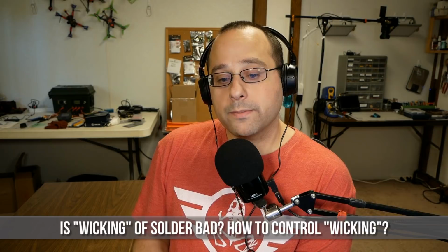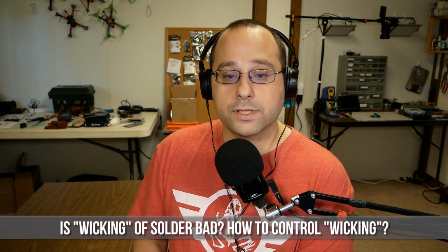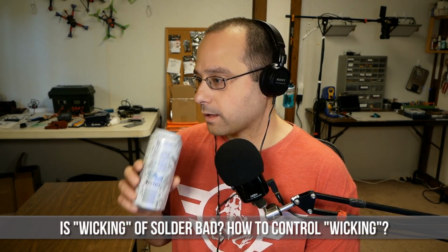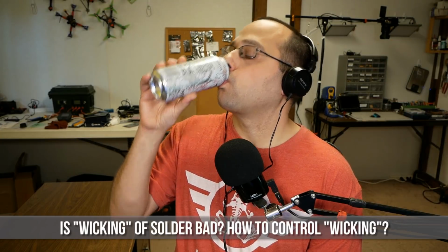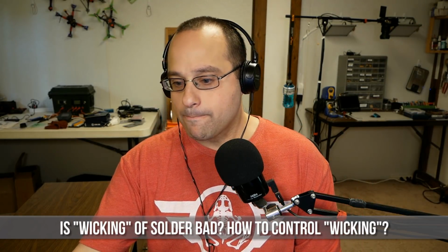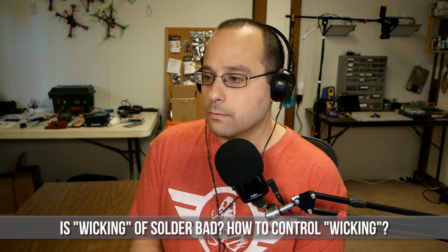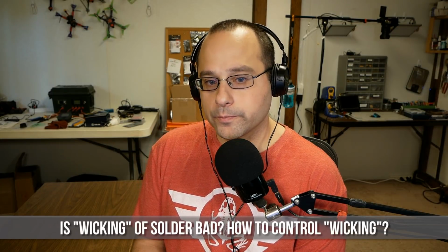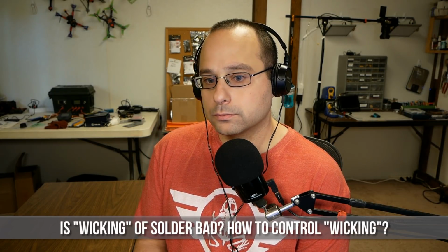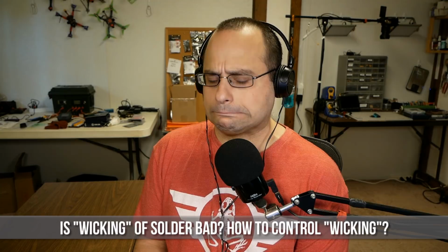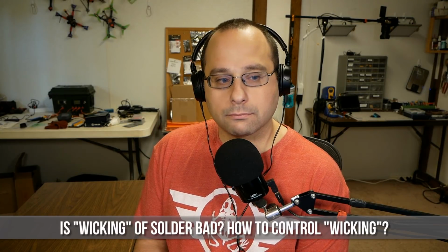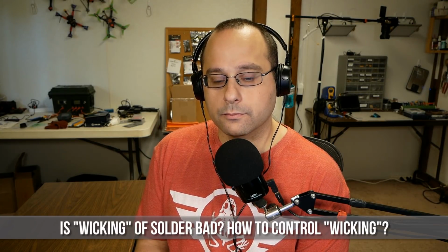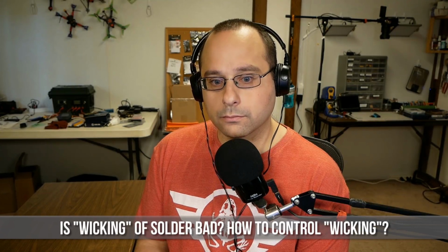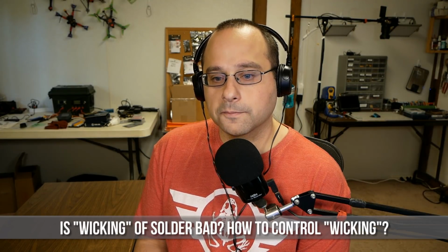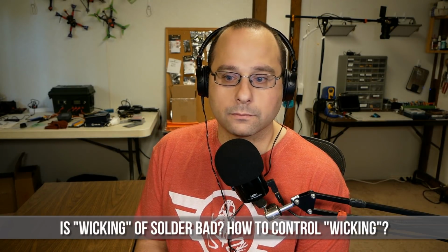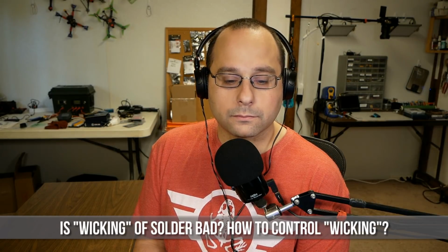What can you do to minimize this wicking if you do desire to minimize it? So you could use a 60-40 solder, which will minimize that wicking because it doesn't flow as much as a 63-37. You could also use some of the lead-free solders, which also don't wick as much as the 63-37, like a tin silver, like a 96.5 tin, 3.5 silver, if you want to do that. So some of those solders will not spread as much as the 63-37.